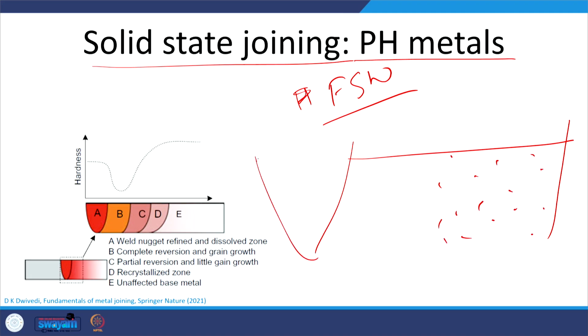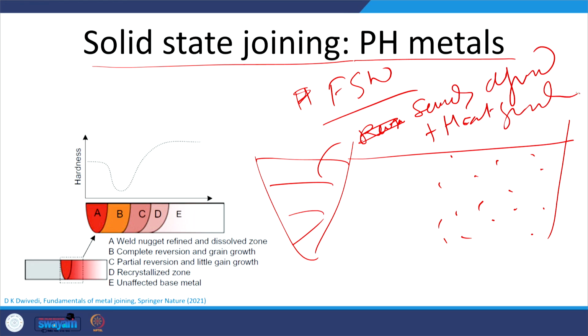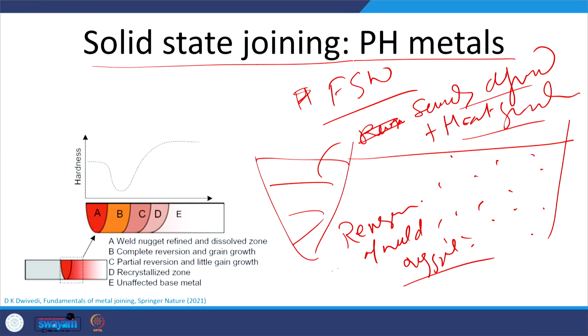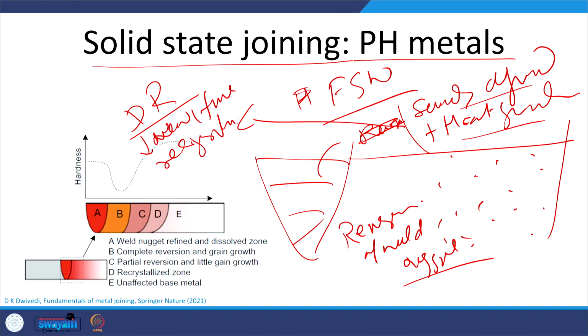So, when the plastic deformation is carried out, the metal is severely deformed, coupled with the heat generated, and the heat generated is also significantly high to cause reversion in the weld nugget area. So, two things happen: severe plastic deformation coupled with the heat generation causes dynamic recrystallization. This dynamic recrystallization forms new fine recrystallized grains, where everything has been eliminated as far as the precipitates are concerned; everything has been dissolved.